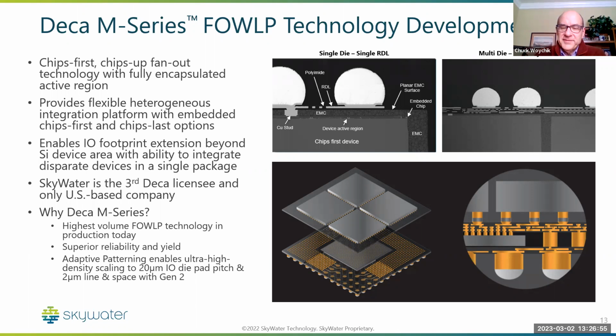The slide over to the right shows two die chips first kind of construction, and below that gets into a much more sophisticated design where you have an embedded die in the core, chips first die. But in addition, you have buildup layers, 3 buildup layers in the top side, 2 in the back side, with a through mold plated via. And what this shows nicely is that you then can have a chips last, which is shown here, attached with a solder cap copper pillar in the top. And then the backside can be solder attached to the next level, which would be a substrate.